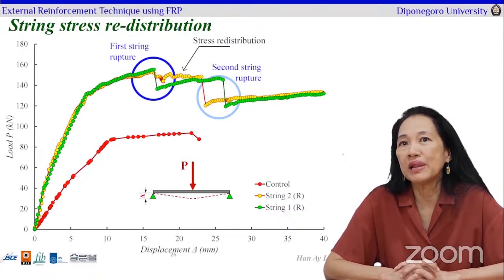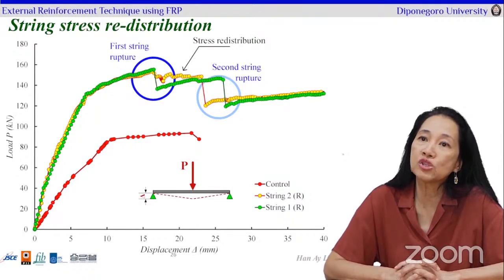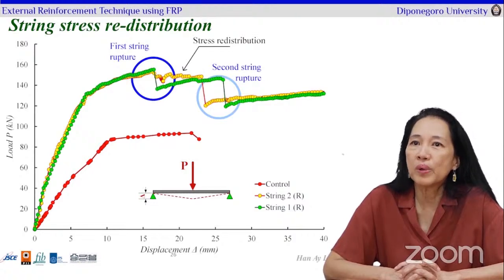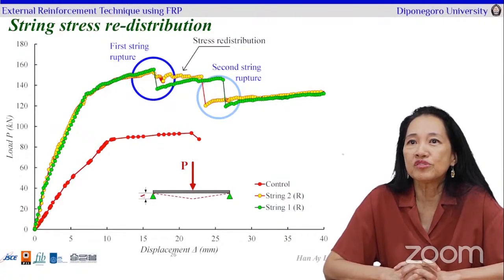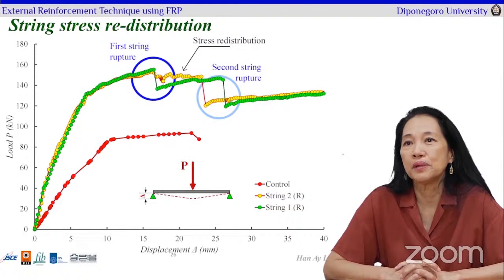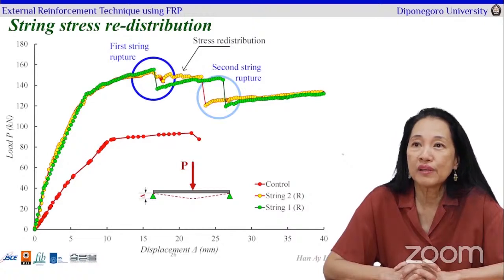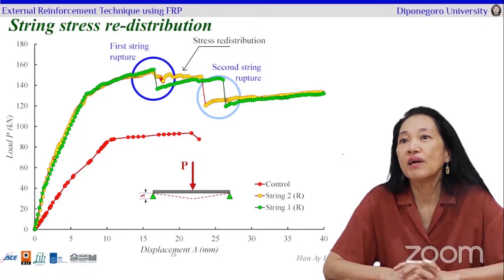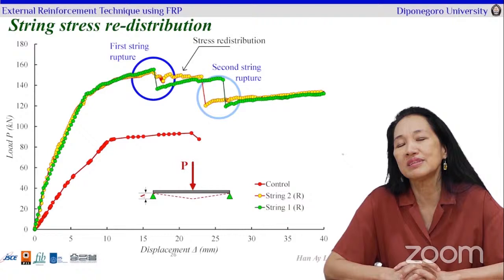For the string and the plate, we had stress redistribution. So what happened, because we were using 2 strings and 2 plates, they did not fail at the same moment. So you can see all the way the load went up, and then the first string ruptured in the blue circle, and it went down, but then the beam underwent redistribution of stresses. The load was divided to the other string, and finally the second string ruptured. So if you can see the end result, still there was a substantial ductility improvement.